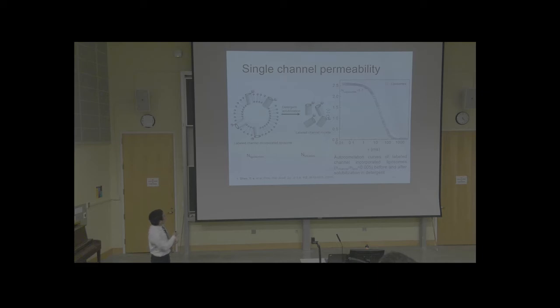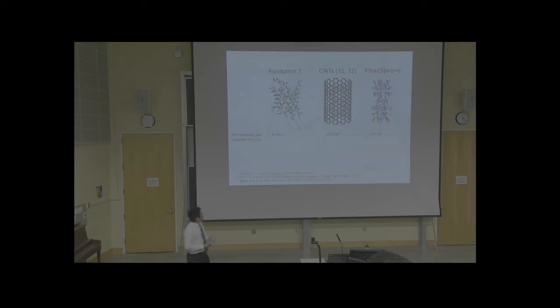So now one particle decomposed into four independent micelles, right, surrounded by this detergent. Then we test in the fluorescent microscope again, and then we get another autocorrelation function. You can see that we can calculate the number of micelles. So based on the number of micelles divided by the number of liposomes, we know how many channels are inside each vesicle. In this case, it's not four. I think it's 500 per vesicle. So based on this information plus the overall permeability, we can know the single channel permeabilities.